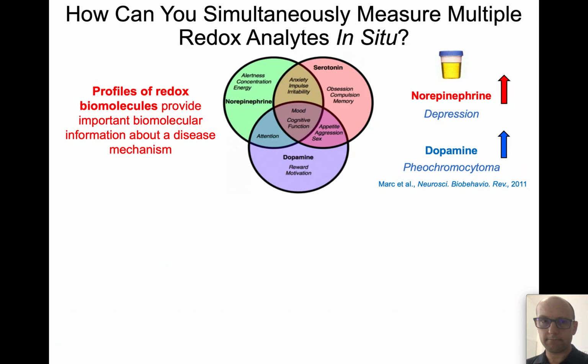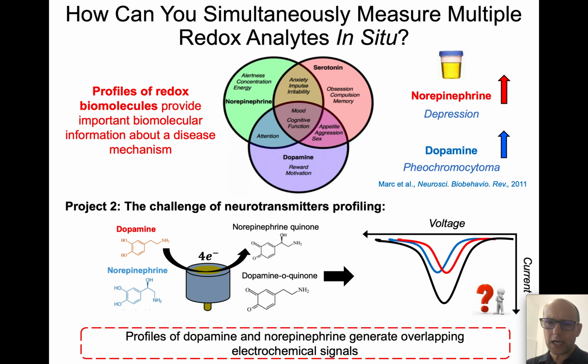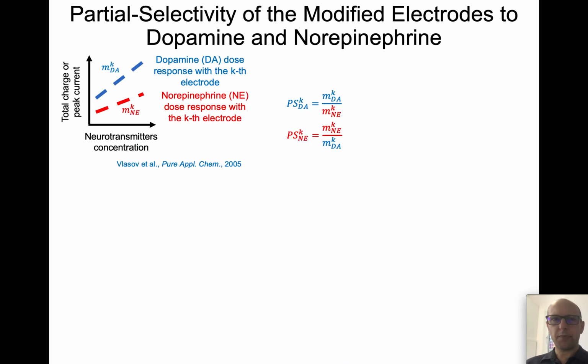So we tested our system in a proof of concept study on the ability to differentiate the signals of norepinephrine and dopamine, which are two different neurotransmitters, directly in urine. And we chose them because their signals are highly overlapping. The first part, we wanted to see what the partial selectivity is, if the electrodes are more selective to dopamine or norepinephrine, because eventually we want to have partially selective electrodes.